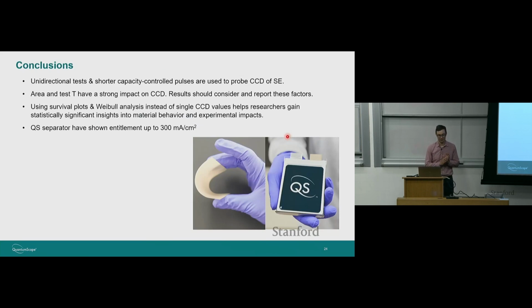Just to summarize our test, we showed some ways to validate that our test gives us valid data, that our pulse length, the style of test we run where we're passing current in one direction is a valid test, and we're using it to probe the critical current density, which is a key performance indicator of a solid-state electrolyte, that there's an area and temperature scaling that are well behaved and have good underlying physical reasons for them, that we are showing the field that using survival analysis and Weibull analysis instead of single point values that are commonly reported helps researchers to gain statistically significant results, and that our separator has shown entitlement to pretty unprecedented levels.